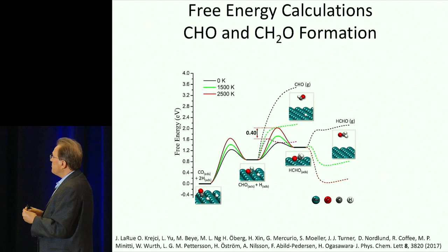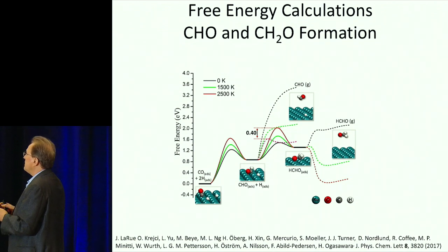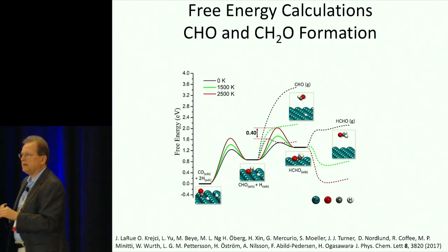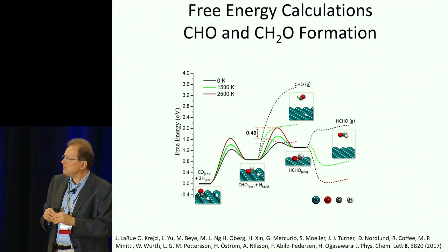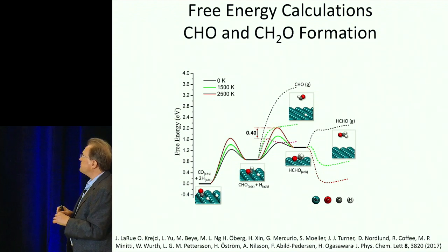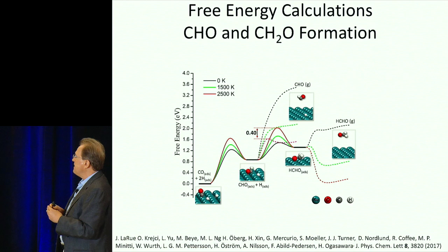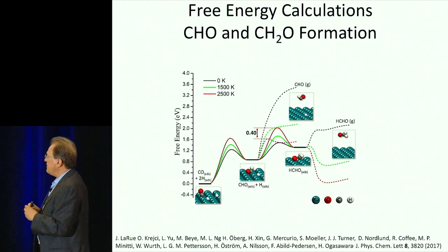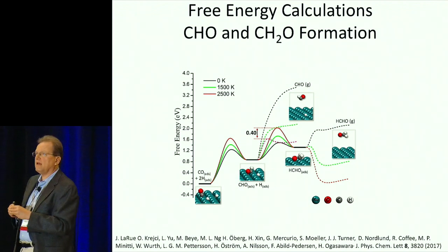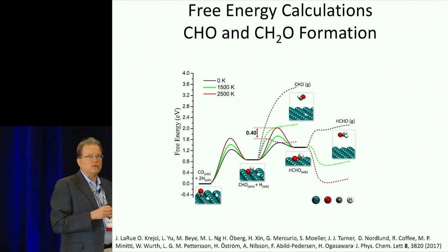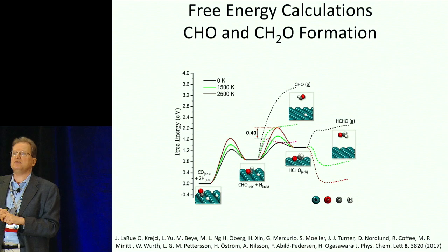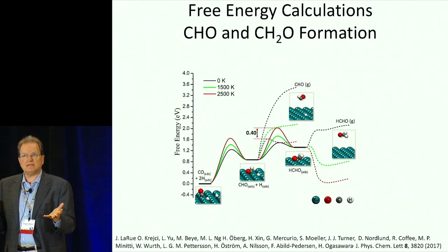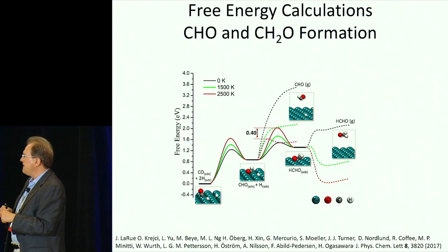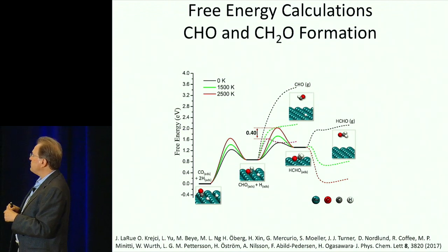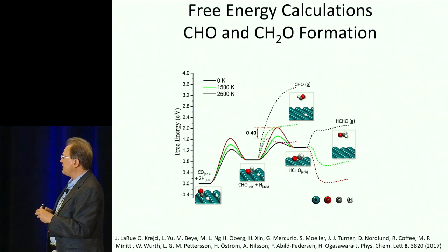So then we went into the theory, and this particular calculation was done by Frank Abild-Pedersen. What you see is a free energy diagram, so to speak, as a function along the reaction coordinate. You have different temperatures here. And let's just look at it at very low temperature. You see CO plus H, and then you see it going over the transition state, and then you see the final CHO being formed. And you see the CHO is actually at higher energy than the CO plus H, which means that it's not stable, it's metastable. We can go further also to formaldehyde, which is even higher in energy.